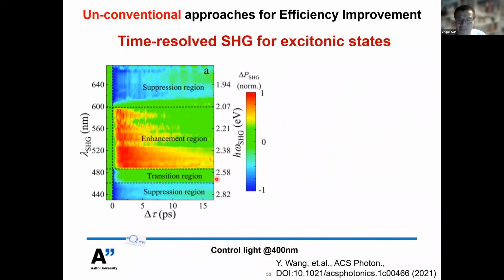If we change the probe wavelength, we find even more interesting results. For a very broad spectrum range, we can find the enhancement of second harmonic generation for some spectral regimes. And we also find some suppression regimes for some wavelengths.